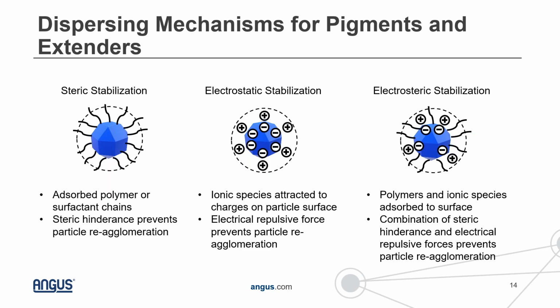Another way is through electrostatic stabilization. This is through the creation of an electrical double layer, essentially, where you have ionic species that are attracted to charges found on the pigment particle surface. They essentially create an electrical repulsive force between particles. So, just like steric stabilization, if two particles try to come into contact with one another, they'll be repelled from one another, and you won't get that reagglomeration.